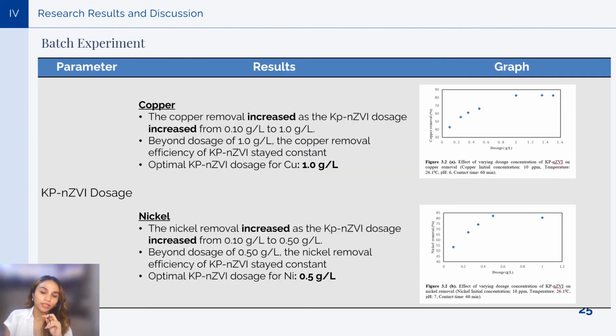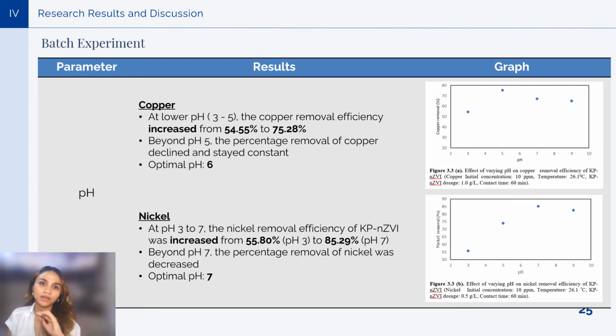The first parameter to be observed at the batch experiment is the dosage of the adsorbent. For both copper and nickel, the heavy metal removal increases as the dosage of the adsorbent increases. Beyond the optimal dosage for both heavy metals, the efficiency of the KP-nZVI stayed constant. The optimal dosage for copper is 1 gram per liter, while the optimal dosage for nickel is 0.5 gram per liter. The second parameter is the pH.